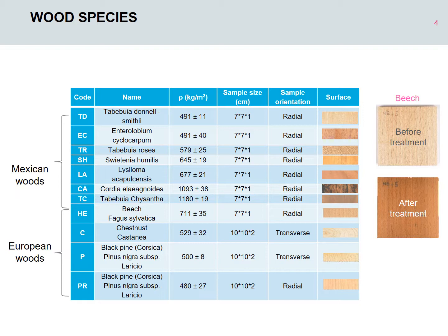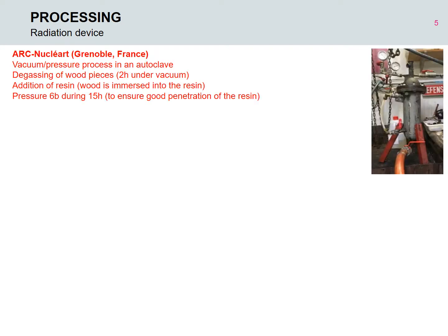For this study, we have used several woods from Mexico or from Europe. The density ranges from 500 to more than 1000 kilograms per cubic meter, and the thickness of the samples is 1 or 2 centimeters. The processing was carried out at Arc Nucléart in Grenoble, France. In the first step, wood is degassed under vacuum. In the second step, the resin is added and wood is immersed into the resin. And in the third step, the pressure is increased to 6 bar during one night to ensure a good penetration